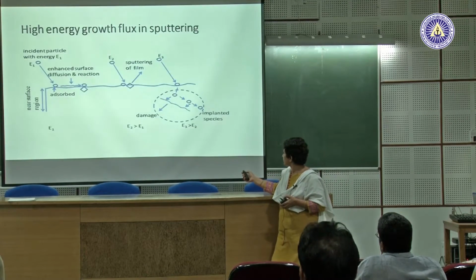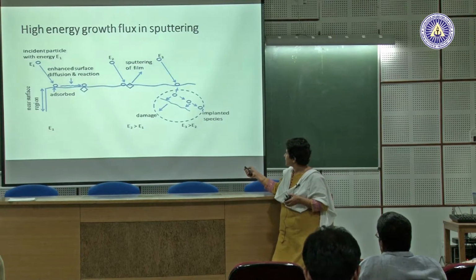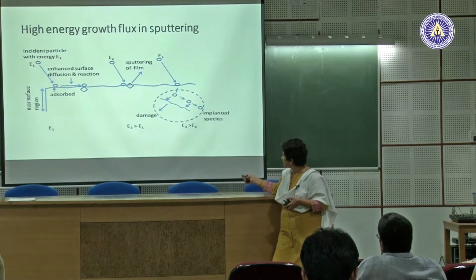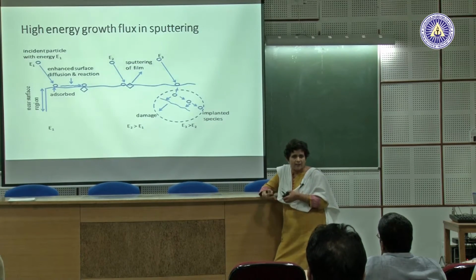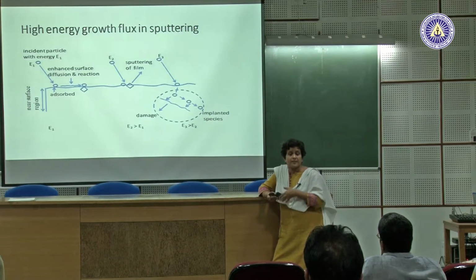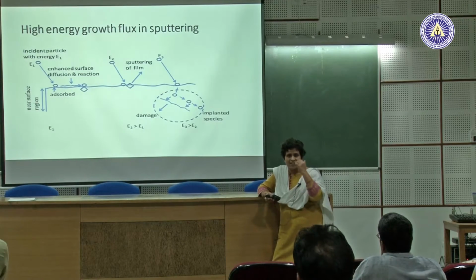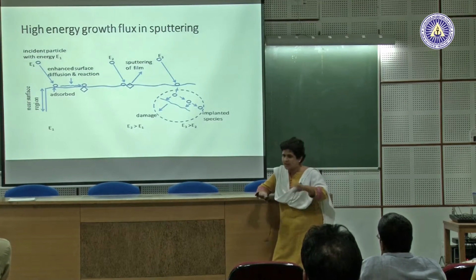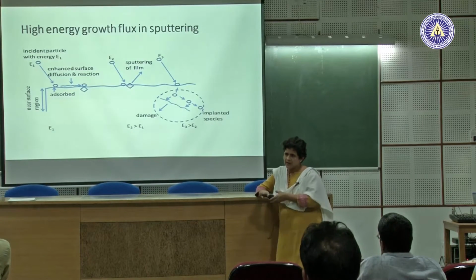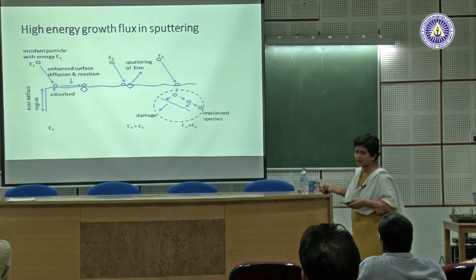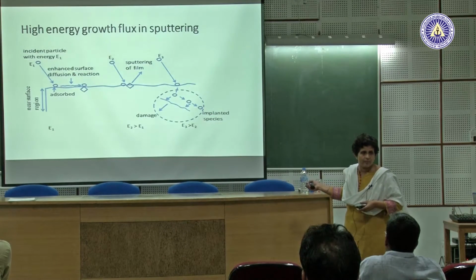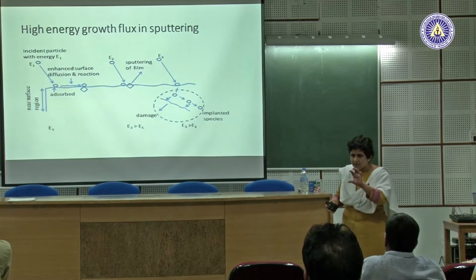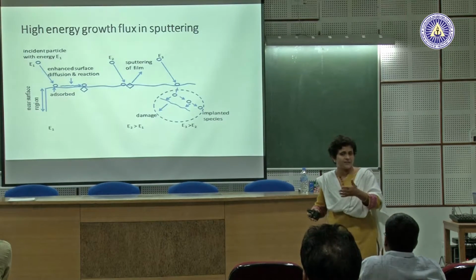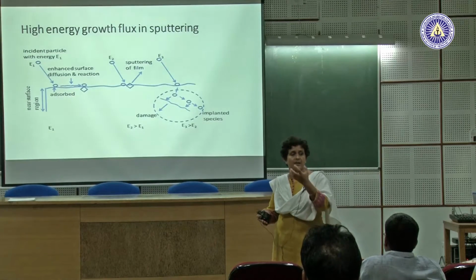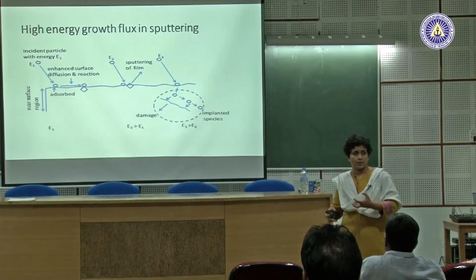So this is the part of that implantation. If the energy is high enough, the atom which is coming gets implanted in the device, and it is providing enough activation inside the film. And this is what makes sputtered films a lot denser compared to thermally evaporated films, because you are continuously giving it a compressive stress. The atoms are coming with high energy, they are moving all the other atoms which are there in the film. And keep in mind that this is all at atomic scale. This will not be more than 10-15 angstrom into the surface. It is not at the surface, it is just in the subsurface region. Things are happening in the subsurface region which are giving your material a quality which would be maybe tensile or compressive depending on the material you are treating.